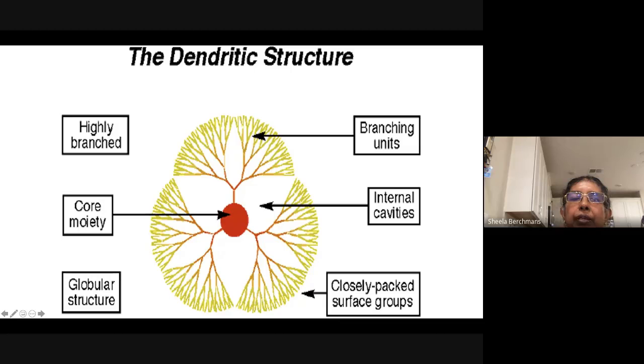So this type of dendrimer molecules have different generations, 1, 2, 3, 4, like that. Different generations of dendrimer are available in the market. We have made use of PAMAM dendrimers for our research purpose. Polyamidoamine dendrimers of 4th generation and 5th generation are used in our work. We have chosen this molecule because in the internal cavities, nanoparticles can be encapsulated. So instead of using a single nanoparticle, a single dendrimer molecule can encapsulate a number of nanoparticles. Therefore, we get an increase in the number of active sites, therefore an increase in the electron transfer rate.